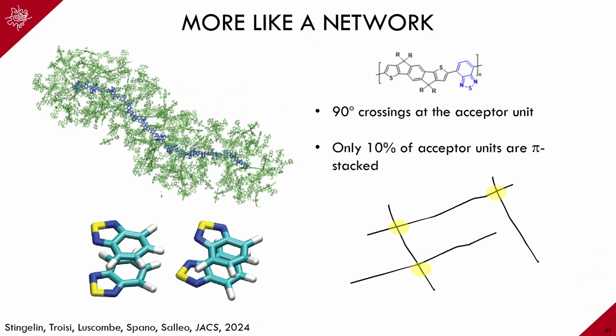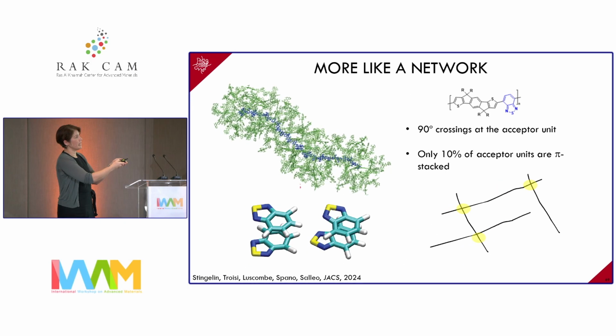But then if you have this needle-like structure, how do you actually get macroscopic charge transport through an entire film? Like, it might be fast along the chain, but at some point it needs to hop to another chain to be able to get from electrode to electrode. And it turns out that what's really enabling that is the following. So the acceptor doesn't have any side chains, so there's a little bit of space. So at that space, these chains cross at 90 degrees.